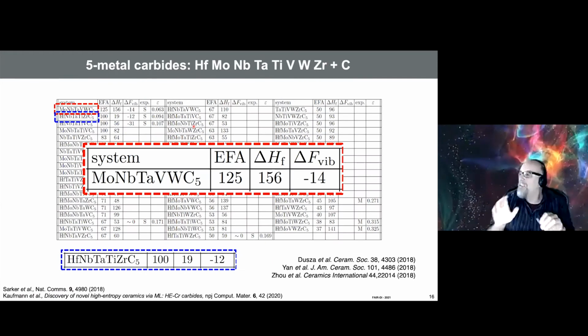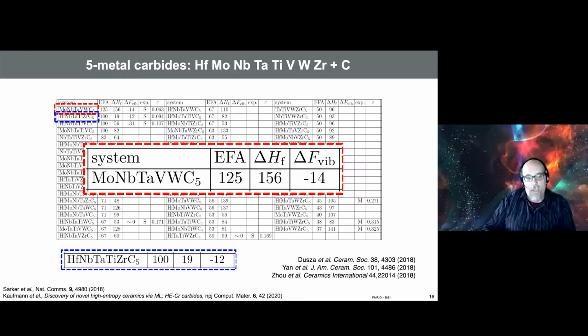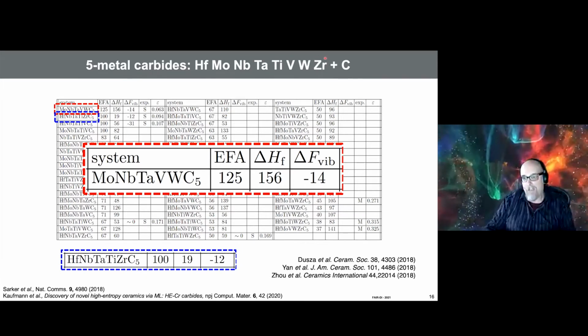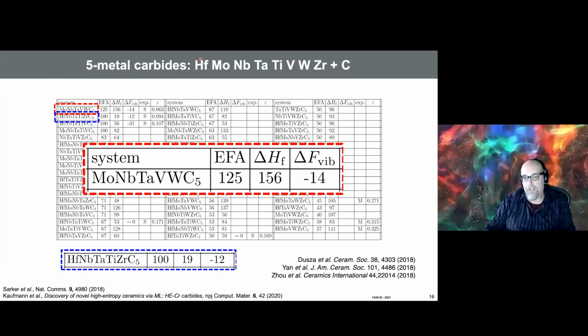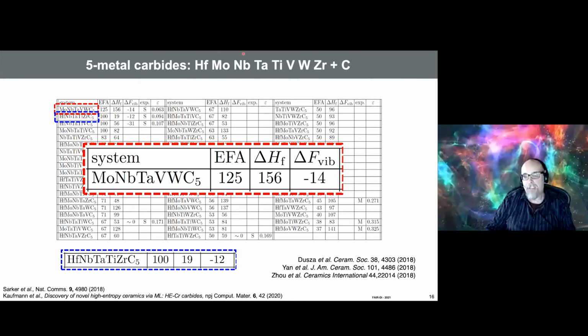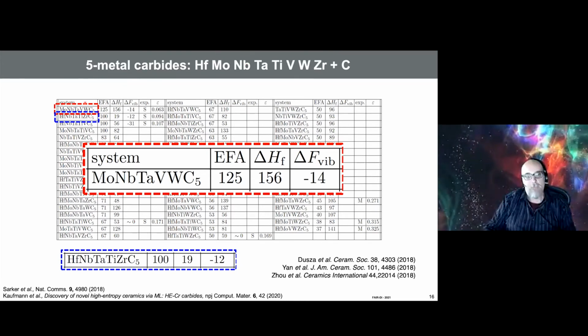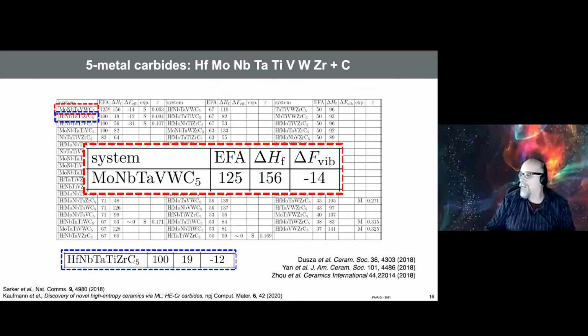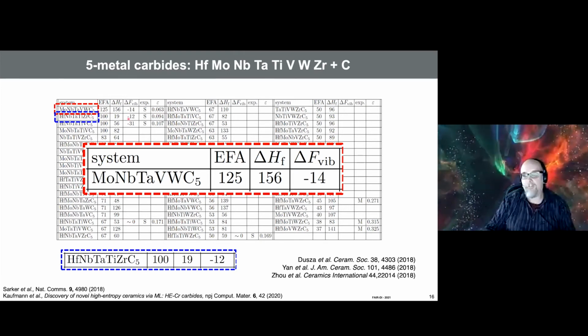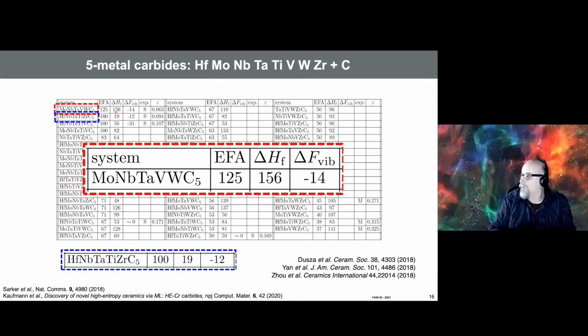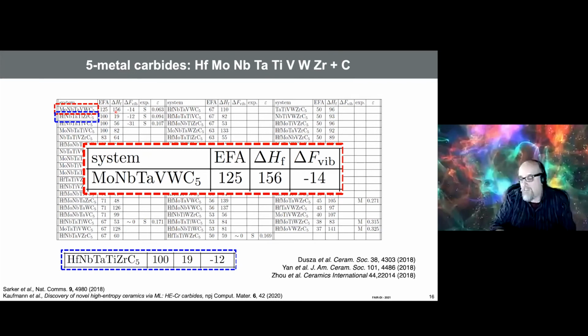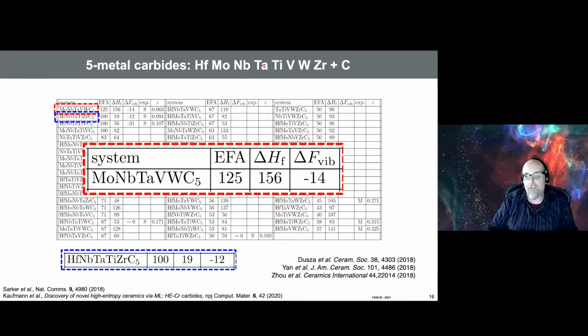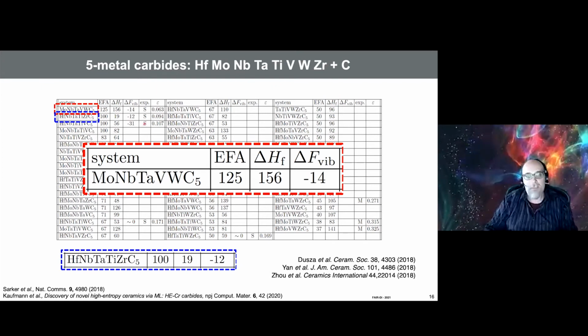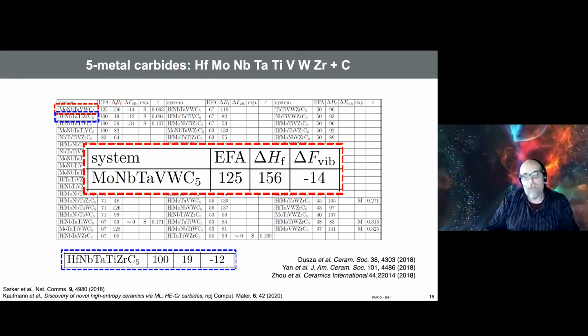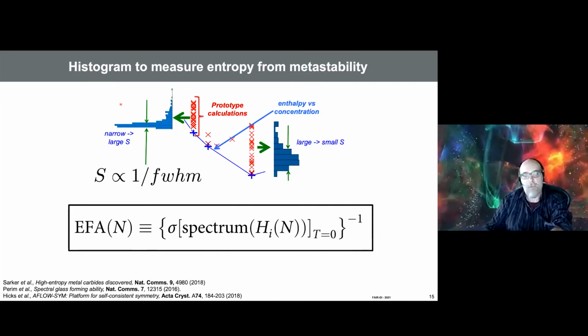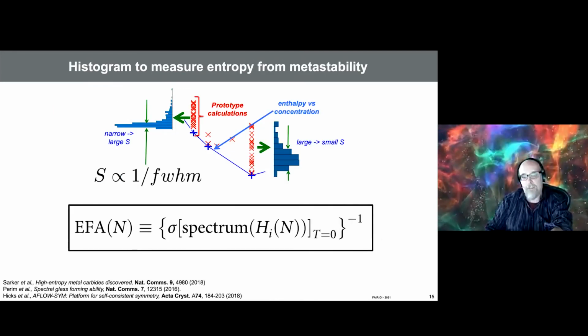Okay. So now let's discover new compounds with big data. Every one of these refractory carbides, so you have eight refractory metals plus carbon, is split in groups of 5 metals plus carbon. For each of them, there are 50 of them, we calculated roughly 100 snapshots. Then from the snapshots, you get the entropy forming ability, and we order them by the entropy forming ability. Then we also plot the formation enthalpy, which is really this distance, the distance between this and the center of the peak.